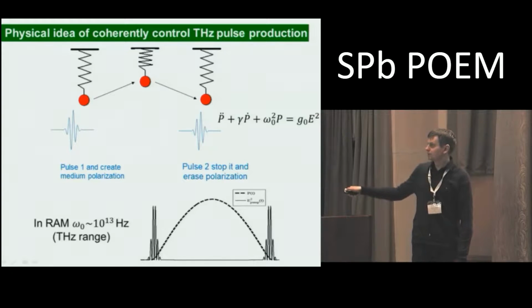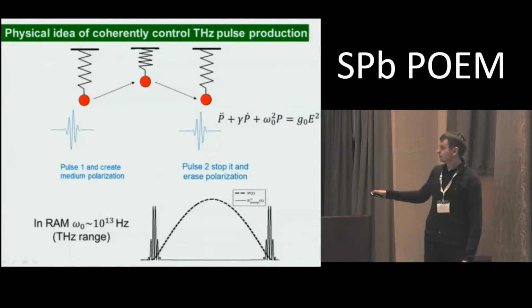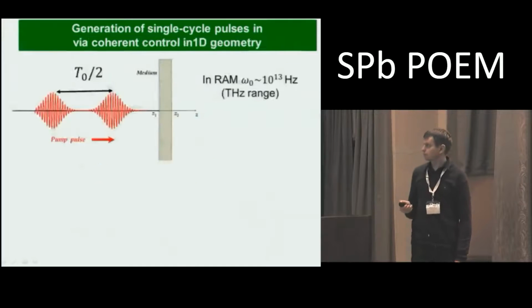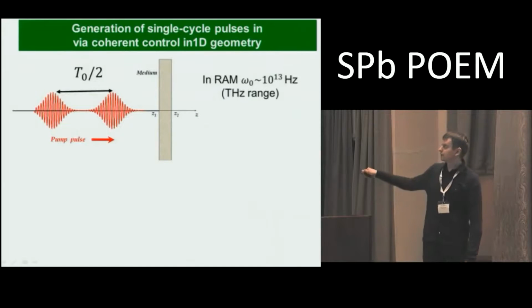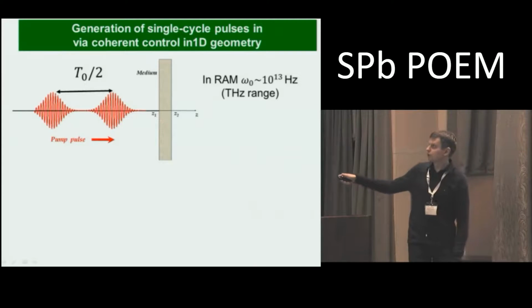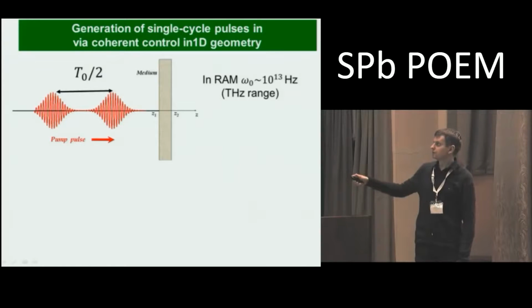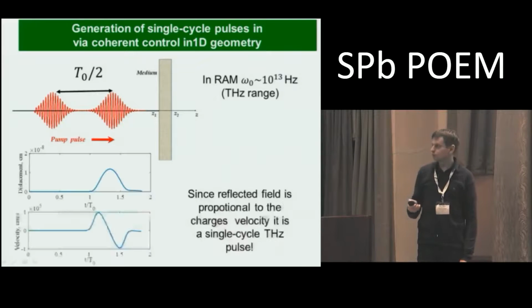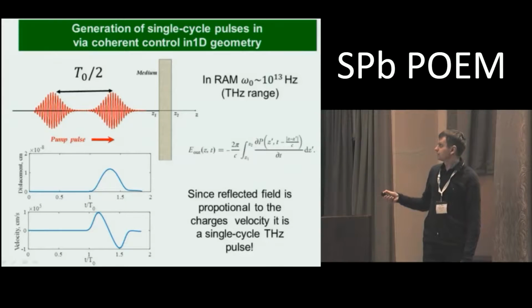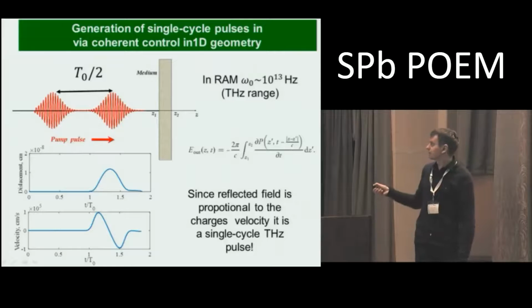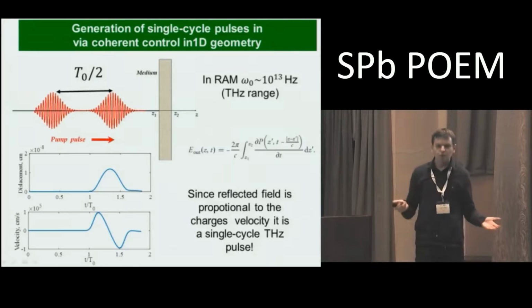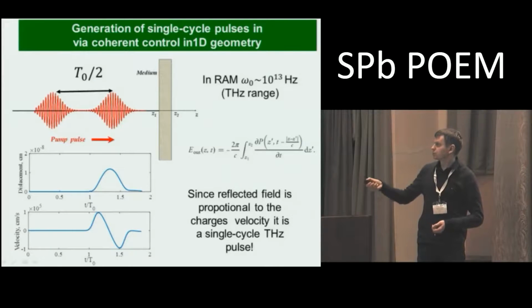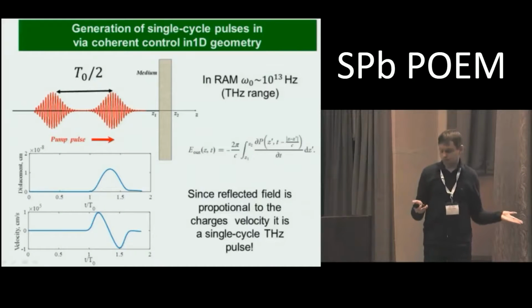Since Raman active media have resonances in the terahertz range, by this method we can generate a half cycle terahertz pulse. So what happens in the one-dimensional case? If you have a thin film, we illuminate our film with the femtosecond pulse train, and the distance between these pulses is equal to half the period of the medium proper oscillations. The medium polarization is a half wave, yes? And as I said on the previous slide, the reflected field is proportional to the charge's velocity, to the first derivative of the medium polarization. The first derivative of the medium polarization, the charge velocity, is a single cycle sinusoid, yeah? Hence, the generated field has the shape of a single cycle terahertz pulse.